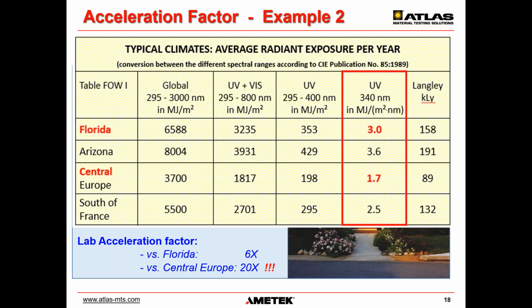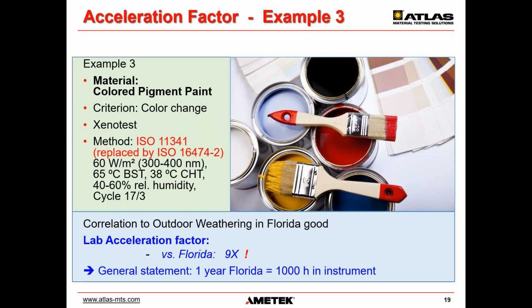What's going on here? Example number 3, also on paints. This test method is actually the same as in the previous example, except that they had more frequent cycling here with a 17-minute light, 3-minute light with water spray, a simple 1/6 fraction of the more common 102/18 cycle in the previous slide. This time the acceleration rate compared to Florida was 50% faster than the previous example, but still over twice as fast as the example in the first slide, the automotive paint and the 4x acceleration.